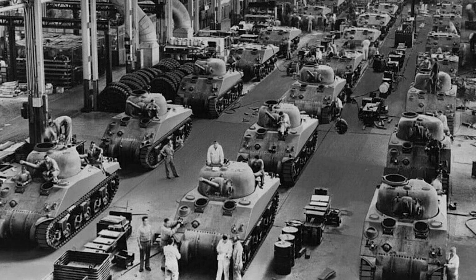about tank armor. First, homogeneous steel plate, steel with uniform composition throughout its thickness, provided the most reliable protection against armor-piercing projectiles. Second, hardness alone wasn't enough. Steel too hard shattered on impact, sending small fragments ricocheting through the crew compartment with lethal velocity. Steel too soft allowed projectiles to punch clean holes through armor that should have stopped them. The optimal range was 260-350 Brinell hardness for thin armor up to 50 mm, dropping to 220-290 Brinell for thicker plates where uniform heat treatment became difficult.